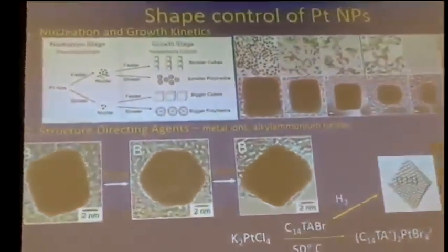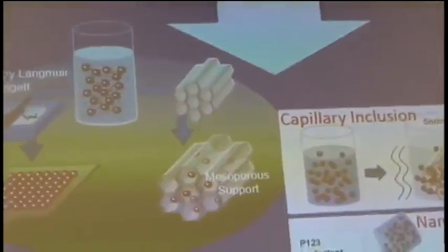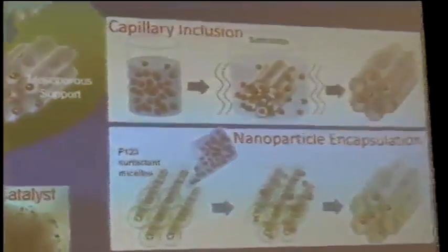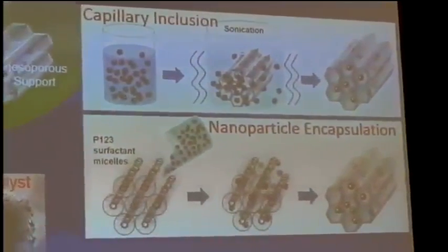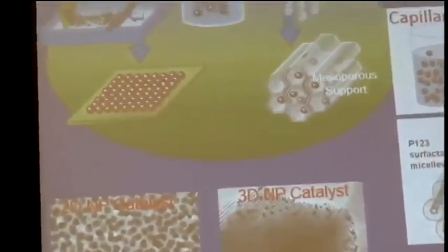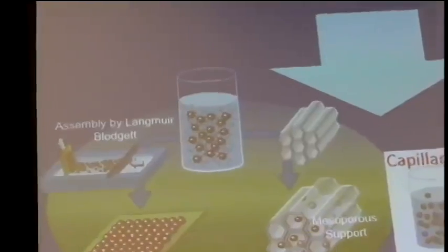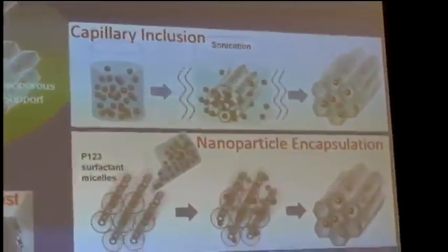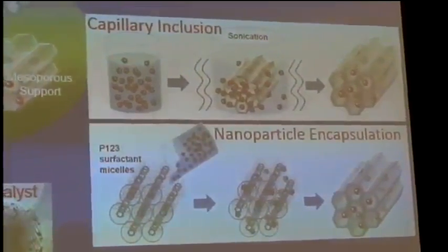Now, when you change the size, of course, the top shows the size dependence of the same shape. You can also change the shape, and both of them are catalytically very significant. So now we go to nanoparticles because it's obvious that it changes the turnover rates and the selectivities, sometimes one more than the other. And so you can do it in 2 dimensions with the Langmuir-Blodgett formation of nanoparticles in various concentration, or by sonication, or other ways you put it into mesoporous materials and you go to 3-dimensional.